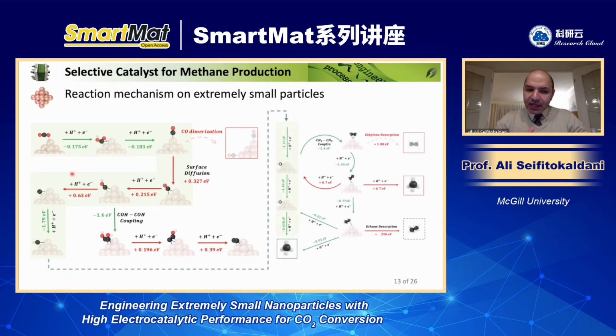But I would say the most interesting part was about the ethylene adsorption. As I said, ethylene was adsorbed on the surface strongly so that it doesn't really desorb from the surface. So this is the interesting part. We followed the reaction mechanism, different possibilities. The highlight here shows the most feasible or energetically most favorable pathway. Interestingly, we are able to produce ethylene even using these small nanoparticles, but then what happens is that ethylene doesn't leave the surface.